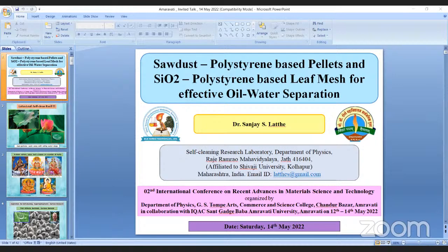We also performed another experiment where mixed oil is separated from warm water, hot water. The kerosene was mixed in water kept at a temperature of 50 degrees Celsius. This kerosene was efficiently separated from the hot water also. Next.